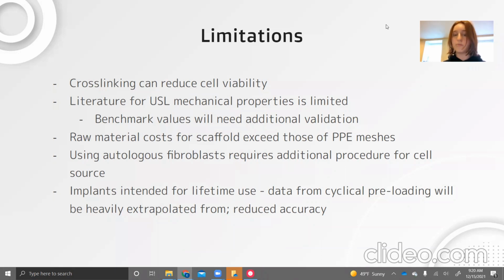Also, using autologous fibroblasts means that we have to source the cells from the patient's own body, which would also require an additional procedure, which is not ideal for patient quality of life. Finally, the implants are intended for lifetime use, which means that any data that we use from cyclical preloading will be heavily extrapolated, as no matter how many cycles you get, it's hard to extrapolate until 20 plus years from now, which will reduce the accuracy of any predictions that we make.